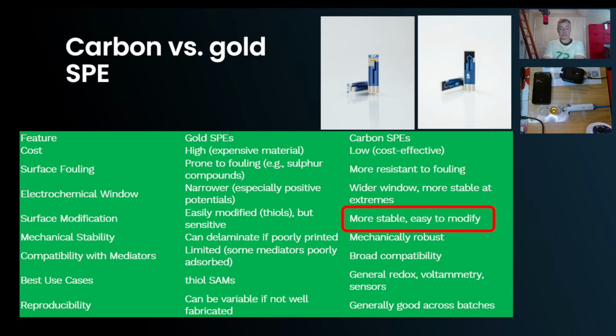Pyrene is quite good because it's got 4 aromatic rings, so it stacks quite well on top of a graphite surface. So I would actually argue that gold has historically been used because it's easy to modify primarily through these thiols, but actually carbon now, there's just as much literature coming up on carbon. And of course, you just have the real advantage of the low cost of carbon versus gold.